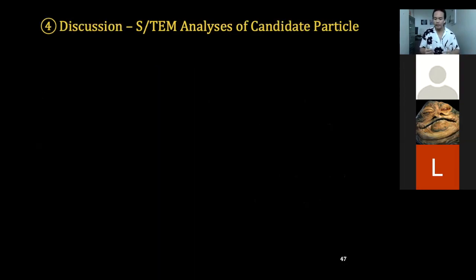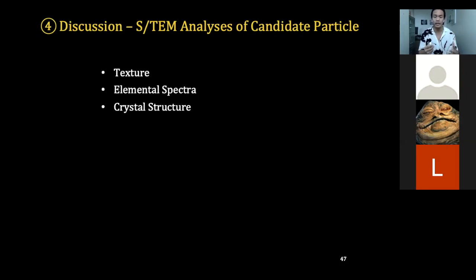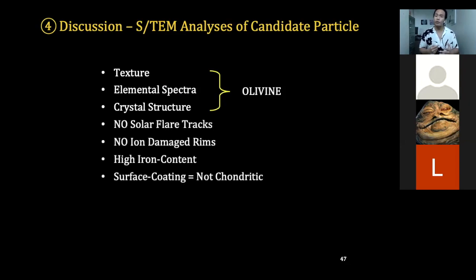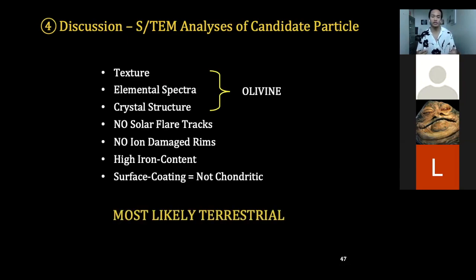To discuss those findings a little bit further, we got textures, elemental spectra, and crystal structure of our sample that all point to it being an olivine particle. However, we weren't able to find any solar flare tracks or any ion damaged rims that would mean that it has spent a significant time in space. Our sample also has a significantly high iron content consistent with more of a terrestrial particle, and the surface coating, which we were hoping to be chondritic, turned out to be clay-like and not chondritic. With all that being said, this one particle that we conducted STEM analysis on is most likely terrestrial. With that being said, we still have a lot of other particles to look at, and we can hope that they may be extraterrestrial.